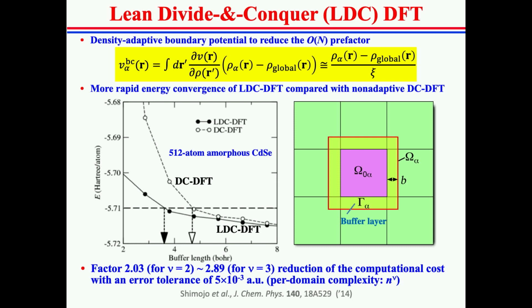But the main problem is the large prefactor of its order-n cost, which arises from the thick buffer layer we need to add in order to minimize the detrimental effect of the artificial boundary condition applied at the domain peripheries. So, in order to reduce this order-n prefactor, our lean divide-and-conquer DFT employs an adaptive boundary condition at the domain periphery, which is proportional to the difference between the local and global density.